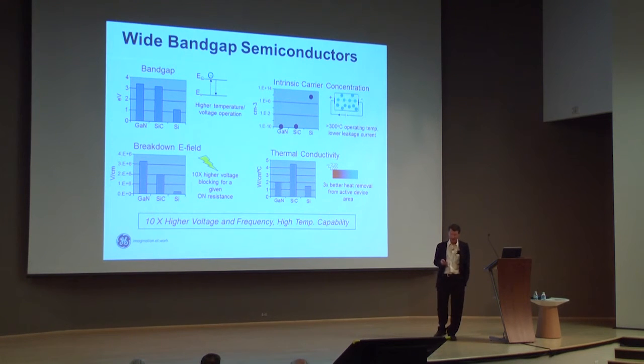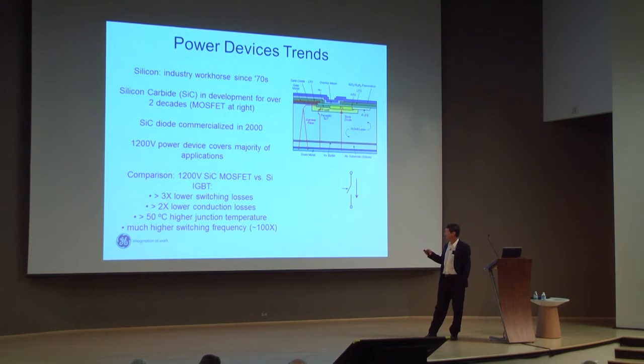Getting now into the wide bandgap area, there's certainly a very new push in power devices, and GE is in the power device area. We're not in the signal chips, we're into power chips. And what we are looking at mostly is silicon carbide. Silicon carbide is a favorite because we think it wins generally when you consider all of these factors. All of these higher bandgap devices have a better breakdown field. Silicon carbide has the best thermal conductivity. Of course, you can run things at higher temperatures with wide bandgap devices because the intrinsic carrier concentrations are down at a given temperature.